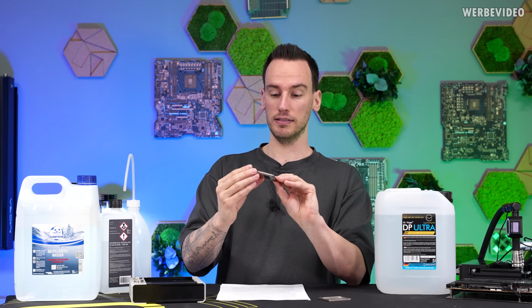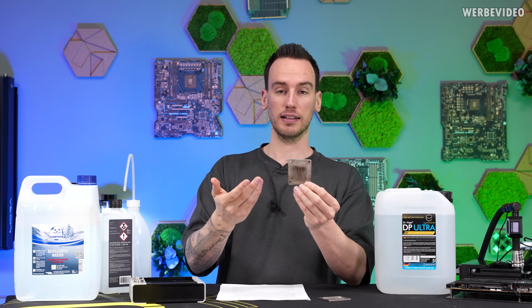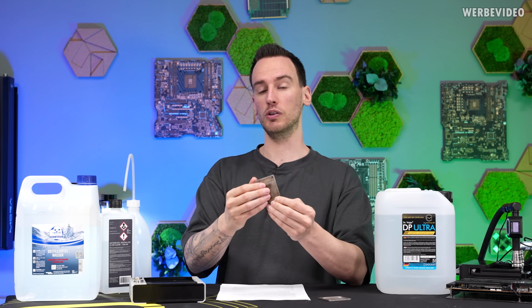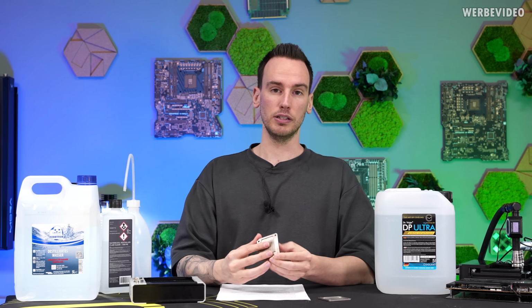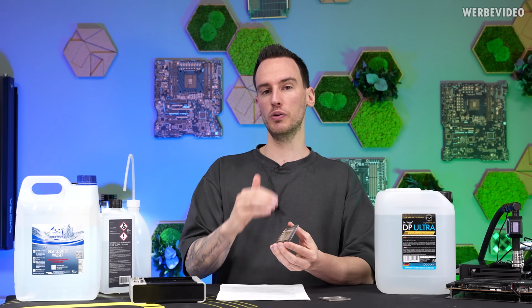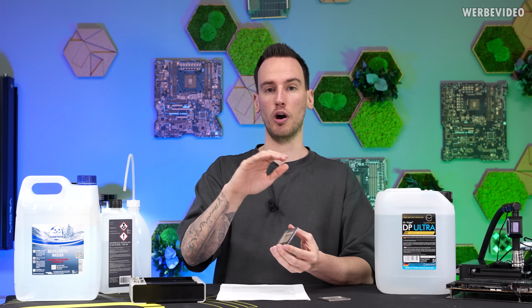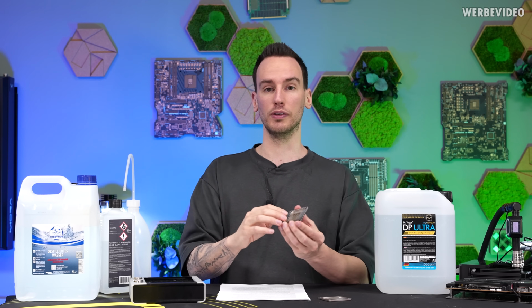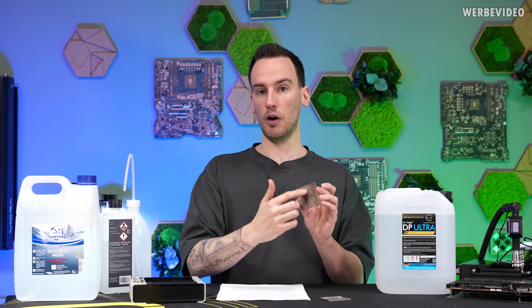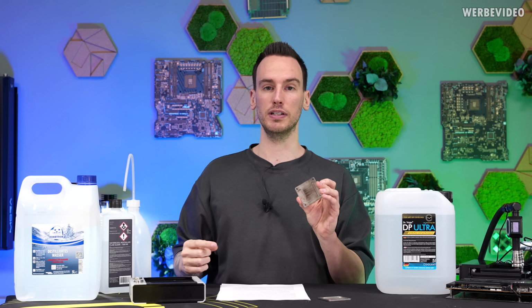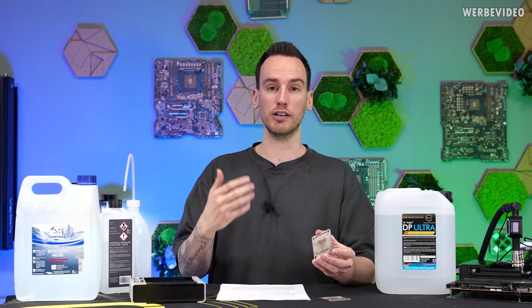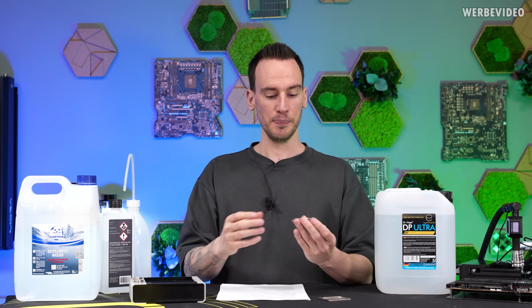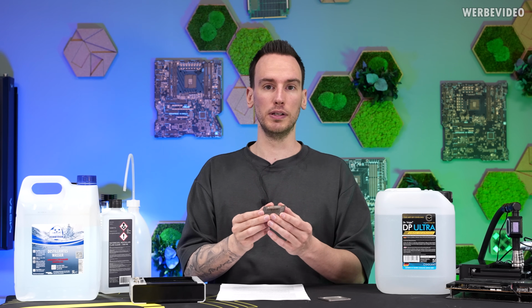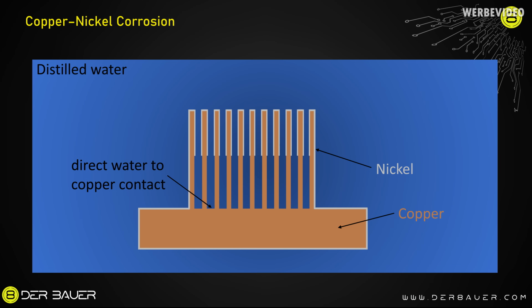And in any kind of piece like this, where you have a very fine structure, you often also saw this in my videos, that if you look in between the fins of some coolers, you can still see the copper, the naked copper, because it's very difficult to nickel plate down into the structure. And sometimes that's even impossible if you, for example, use electroplating, that is also often used. So it's quite common and it's absolutely normal that distilled water would have direct contact with the copper, even though this is, at first look, a nickel plated part.